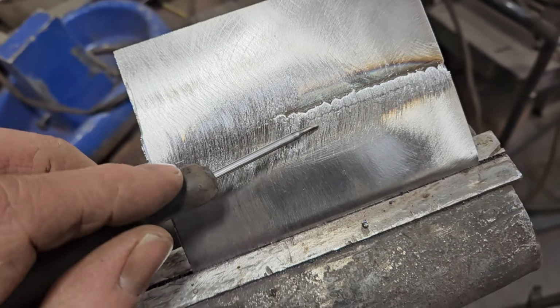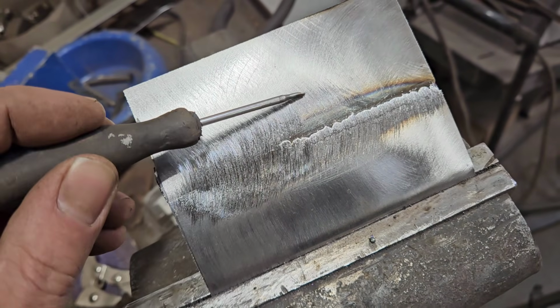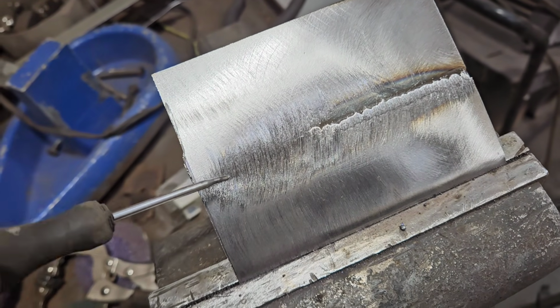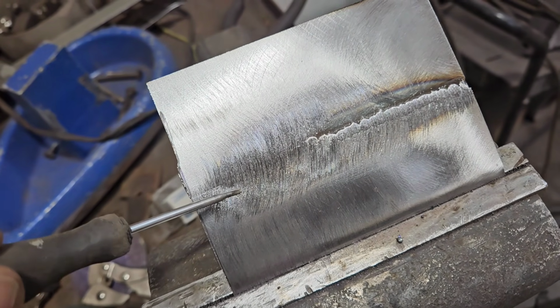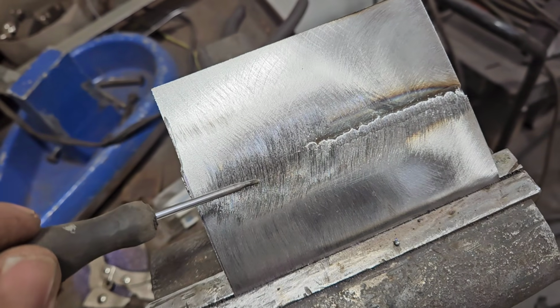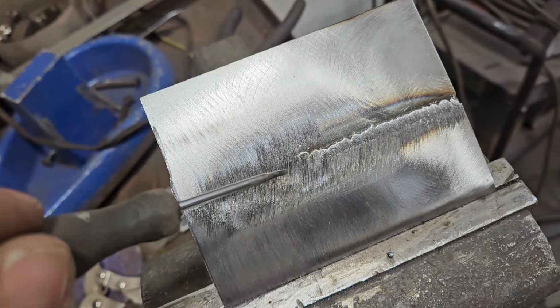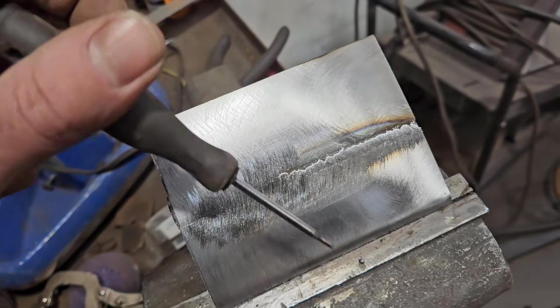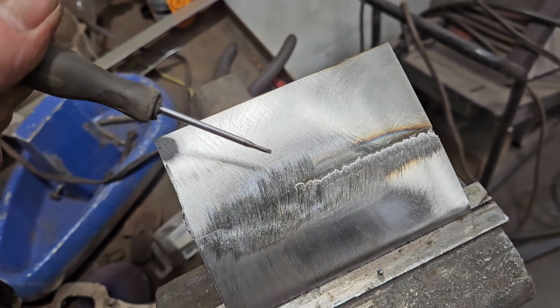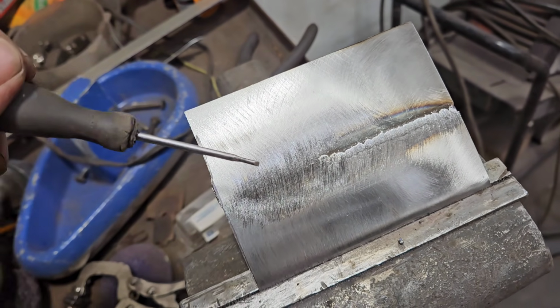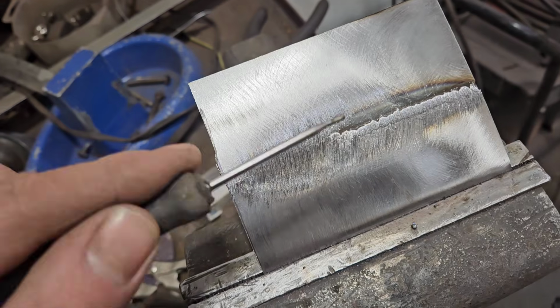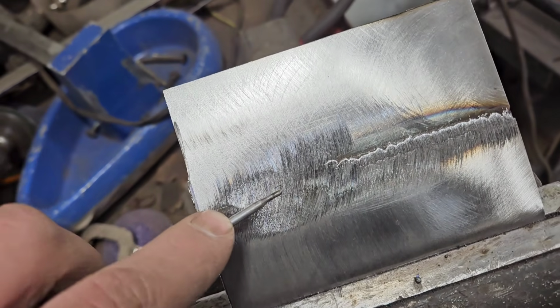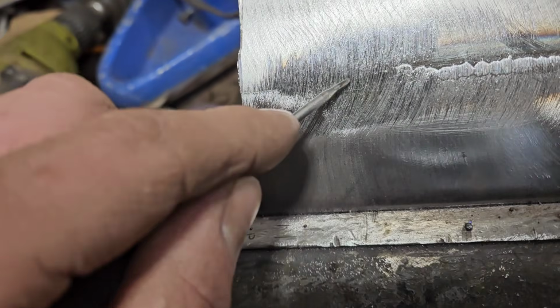What's happened here is because this side is higher than this side and we've gone and ground it, now the metal on this side of the repair has been substantially thinned. And we don't want to thin the metal because we were just replacing thin metal from rust or whatever damage that we were replacing. So, we've just added damage back into the panel.